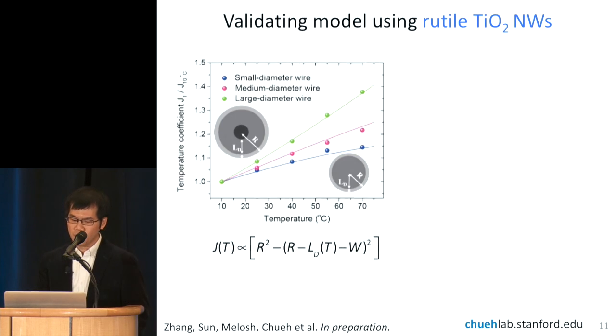And what I'm about to show you is a data set that looks at the photocurrent as a function of temperature for each diameter. And what we have done here is to develop a simple geometric model to fit all the data points for all the samples using one equation. So you can see when the wire is very, very thick, such as the green line over there, it's very much increasing linearly with temperature. So that means as you increase the temperature, you're getting more and more current because you're not running out of wire to absorb the light.